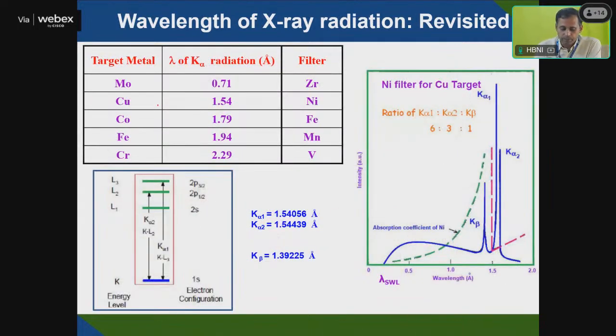As I told, for a molybdenum target you have to take a zirconium filter. For a copper target, you have to take a nickel filter, and so on. And another thing is the target material. For example, if you take Fe3O4 or any iron-based material with a copper target, sometimes fluorescence will come from the iron. Because of that, you get a lot of background. So accordingly, you have to choose your target element to get a proper X-ray diffraction pattern.